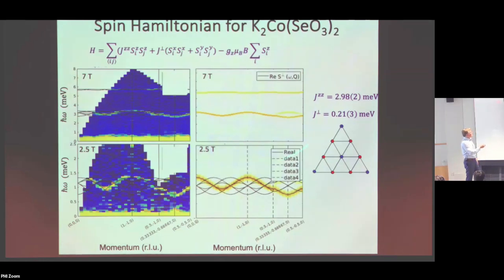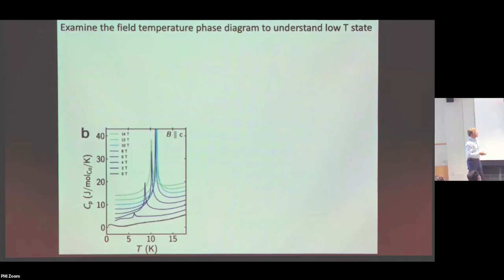And so we can do regular 1/S spin wave theory and calculate the scattering cross section, and we can get these exchange constants, 2.98, consistent with what we saw from the rough analysis. But now we get the transverse part as well, which comes from the bandwidth of this excitation. So it's a direct kind of modeling. That's the calculated, and that's the measured. And it works pretty well. Okay.